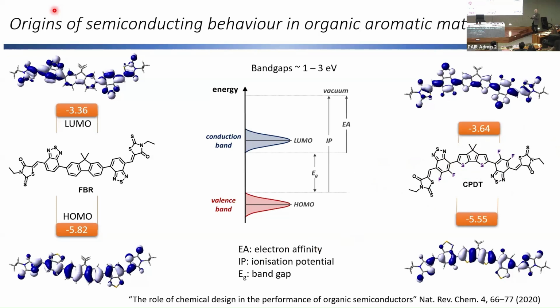And what that does is that gives the molecule at rest more energy, more electron density. And when that happens, you can see we've gone from minus 5.82 now here, to a 5.55. So this has been a significant shallowing due to the energy density increase.